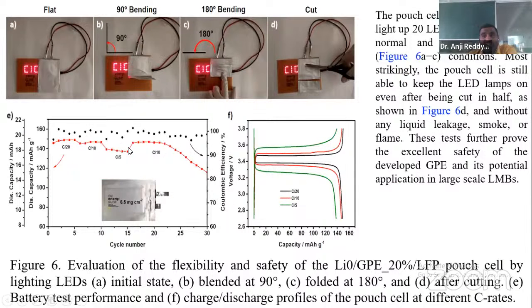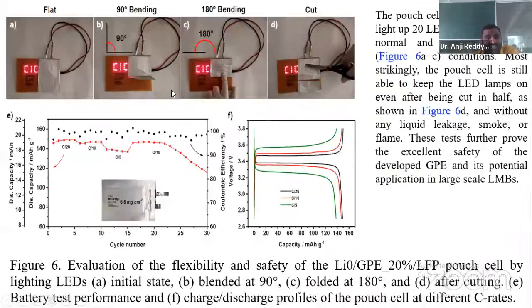And they check it with the different LED lamps. Okay, these are pouch cells, not coin cells. See, these diagrams are for coin cells with different electrode material, cathode material, and these are pouch cell tests. You can observe, this is a pouch cell. This is bending, how much angle? 90 degrees. See, this is a flat one, completely. Around a 20 centimeters square area. Half of the pouch cell is bent at 90 degrees. This is 180 degrees, completely folded. And this is cut.